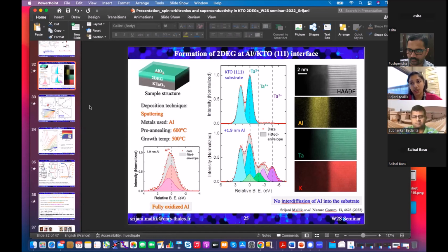But it's possible without doing XPS also. Let's say I don't do XPS, I grow my sample and take it out for transport measurement. Just by transport measurement, I can also confirm that I have a 2DEG in my sample. But anyway, the oxygen vacancies have to be present. Yeah, I mean, that's clear enough.